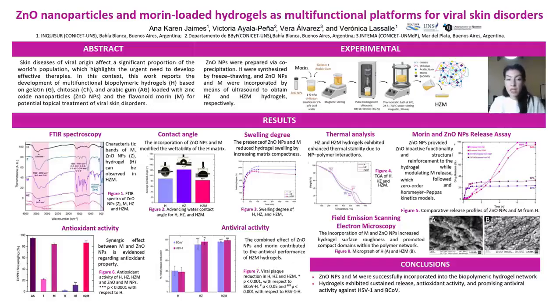In the release study, we evaluated the release of both Morin and zinc oxide nanoparticles in acetate buffer at pH 5 and 32 degrees Celsius, simulating skin conditions. Morin exhibited a sustained release profile and followed zero order and Korsmeyer-Peppas kinetics models, indicating that the release mechanism was governed by diffusion, polymer relaxation, and matrix erosion. In contrast, nanoparticles showed a limited release profile, suggesting that a large fraction remained retained within the hydrogel network.